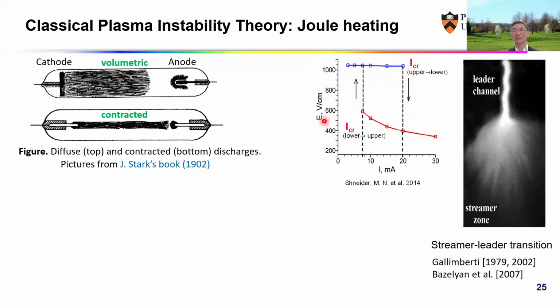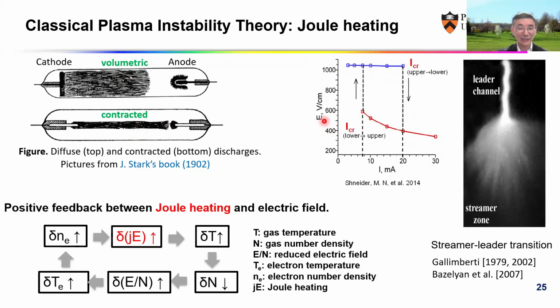I got very excited about this, and I tried to see what the mechanism is. It's very simple. If you have any perturbation in plasma chemistry, an increase of electron number density will increase the Joule heating. The Joule heating will increase your temperature. The temperature increase will decrease your number density and increase your mean free path. So electrons have more energy. When electrons have more energy, they generate more electrons. So this positive cycle just keeps going.